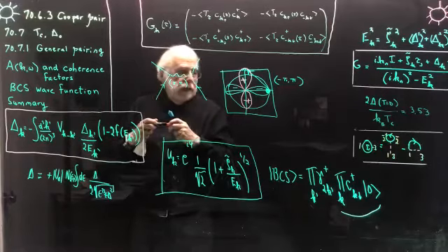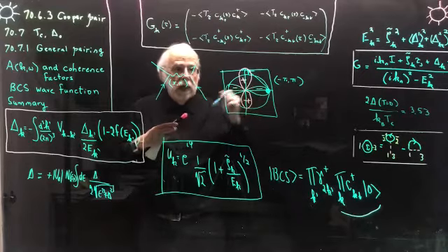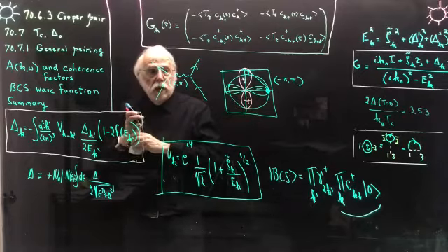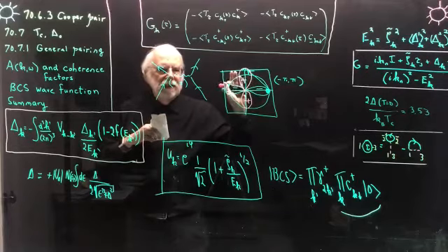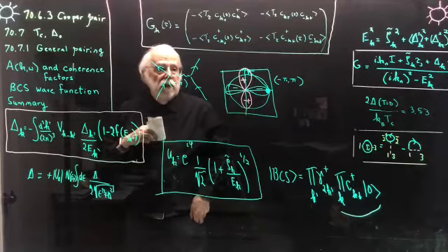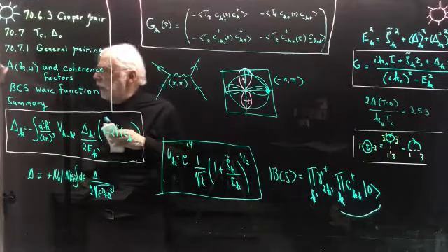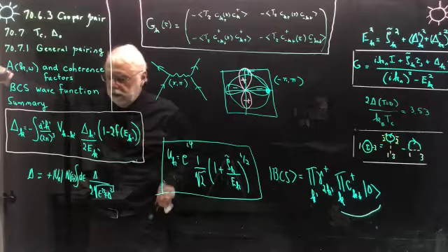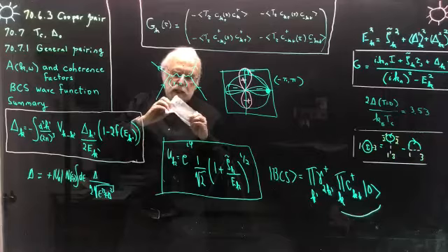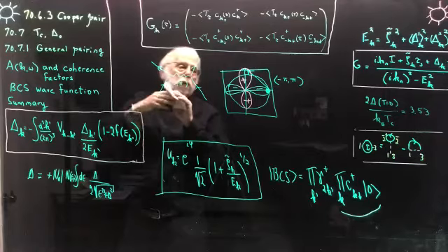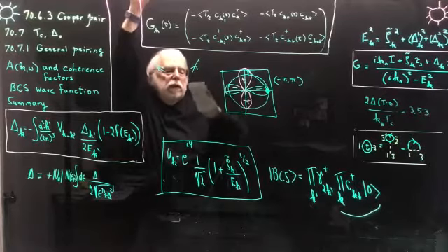And the advantage of this is that also in a D wave, the pair wave function gets to 0 at the origin. So if there are strong repulsive forces, you can avoid them this way. Okay, so that's a very simple-minded, but I think essentially correct way of thinking of pairing, at least when the interactions are not too strong, in systems with purely repulsive forces.